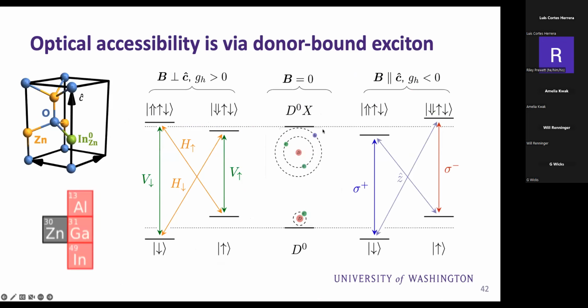Okay, so the optical accessibility is not through just exciting an internal orbital of the defect, but actually comes from exciting an electron hole pair across the band gap of the material itself and creating something called the donor-bound exciton, which is 2 electrons and a hole. These are still very sharp transitions. This transition exists below the band gap of the semiconductor. It's bound, and you can have very well-defined selection rules that are given, of course, by the symmetry of your crystal.